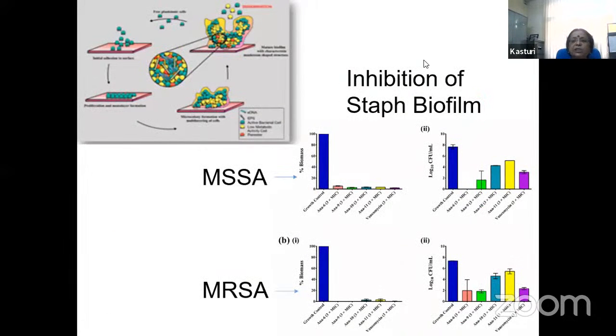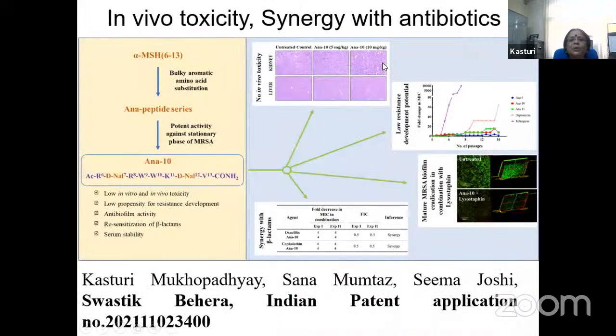Not only that, it inhibits the staphylococcal biofilm. The major problem with staphylococci is that they form biofilm on different kinds of catheters or implants. But these 2 peptides, ANA9 and ANA10, can inhibit this biofilm. We have also done in vitro cytotoxicity and in vivo toxicity. They don't harm the kidney or liver of the mice, and there is no development of resistance against them. Also, they are synergistically active with oxacillin and the beta-lactam antibiotics. That's the most important observation.